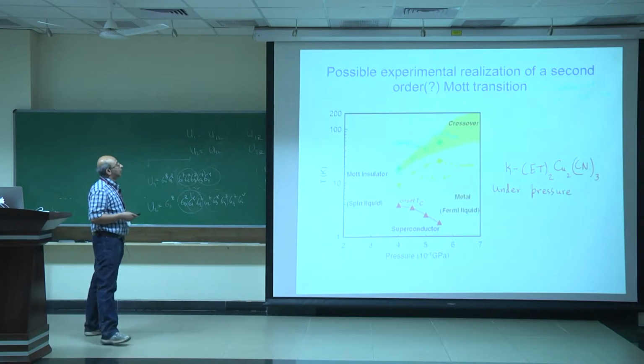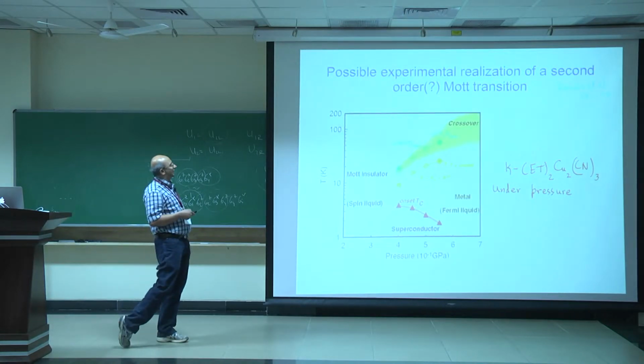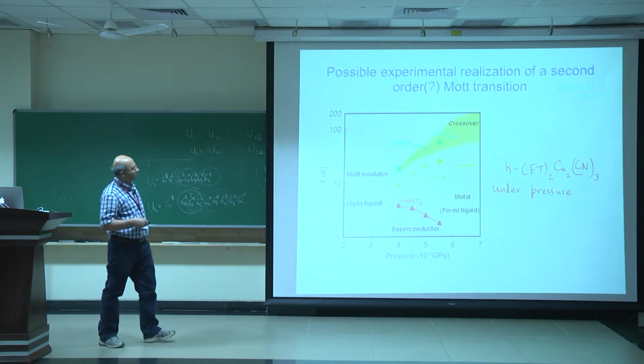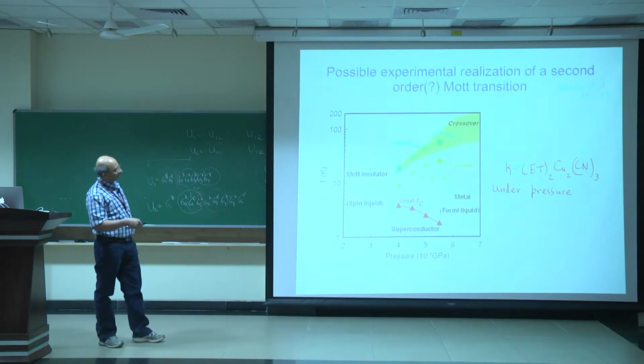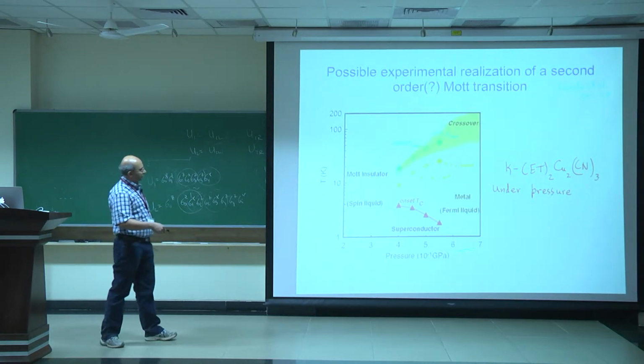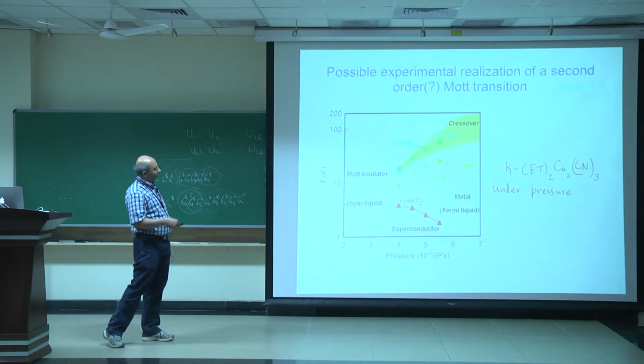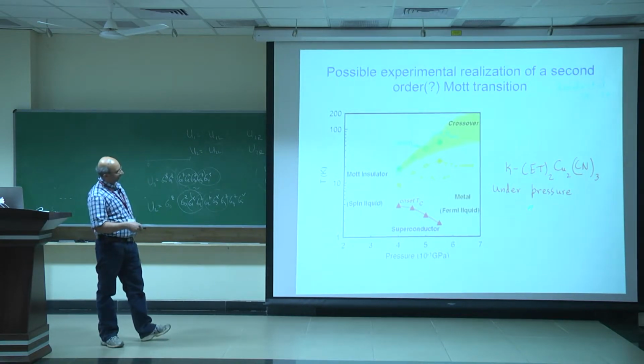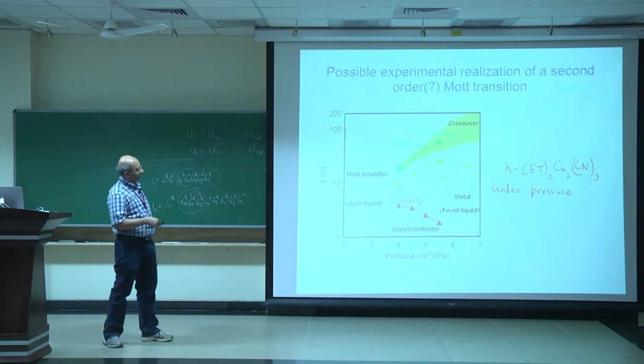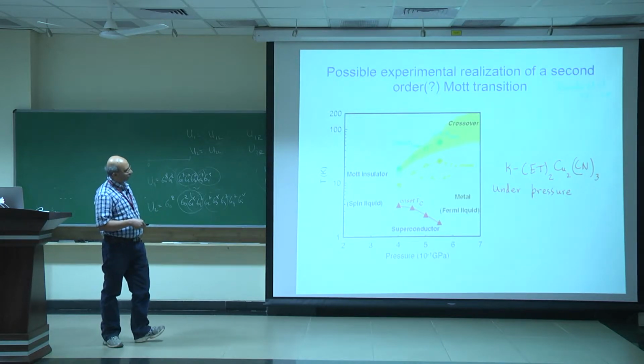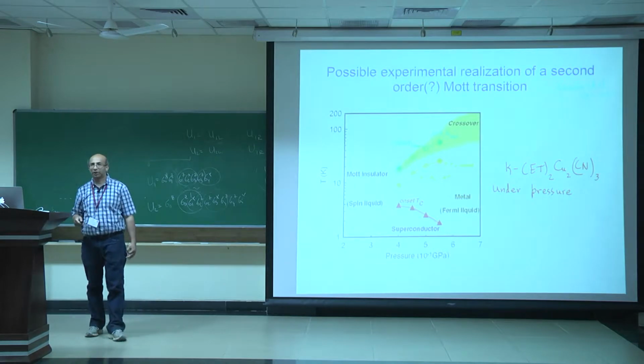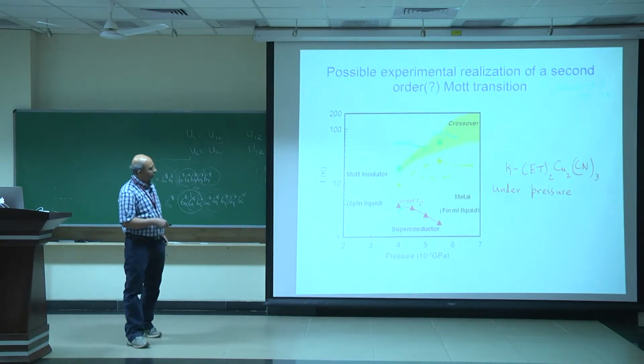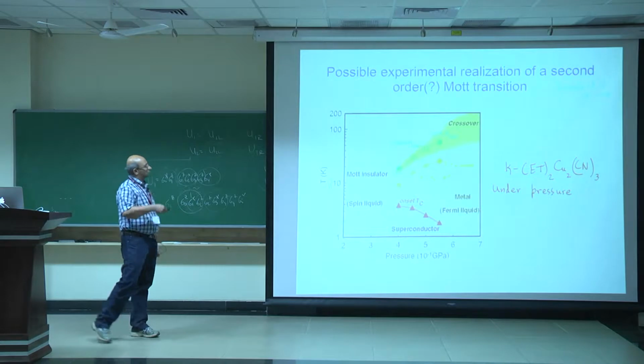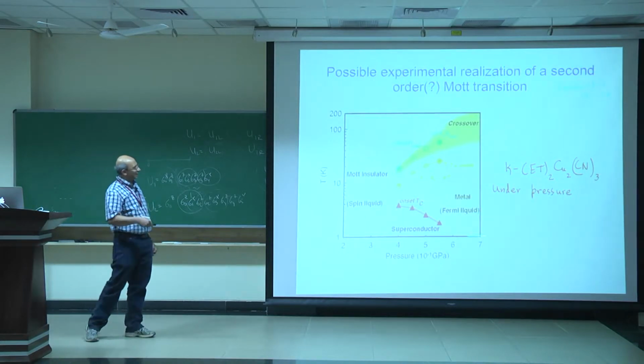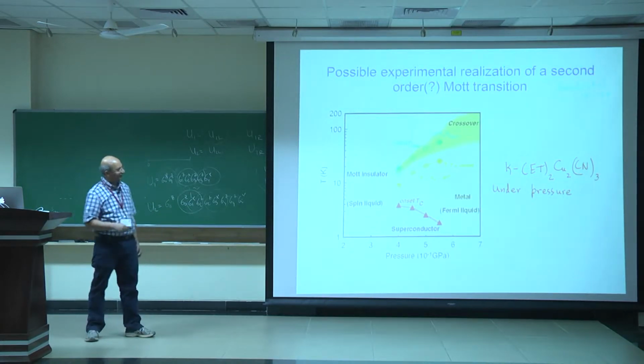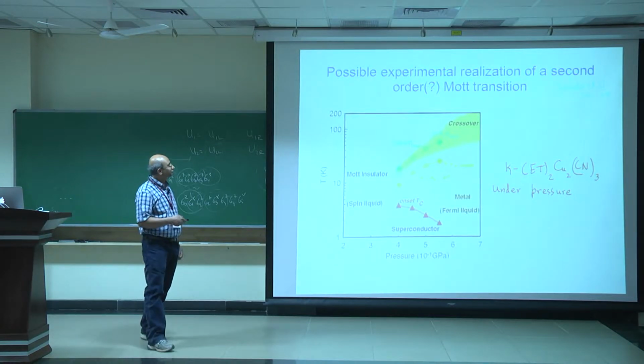Okay? And there's a possible experimental realization of a second order Mott transition in one of these organics, kappa-ET. So as a function of pressure, it goes from a Mott insulator to a metal, quite likely a Fermi liquid, through a transition which, if at all it's first order, is only very weakly first order. Okay? There's a small blip of superconductivity here, below 3.5 Kelvin, but on the big energy scale that characterizes this phase diagram, this is a tiny, tiny region which we won't focus on.